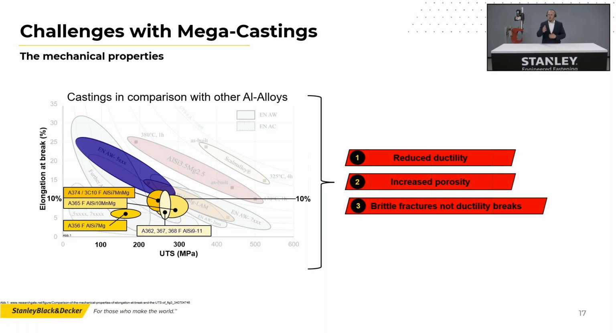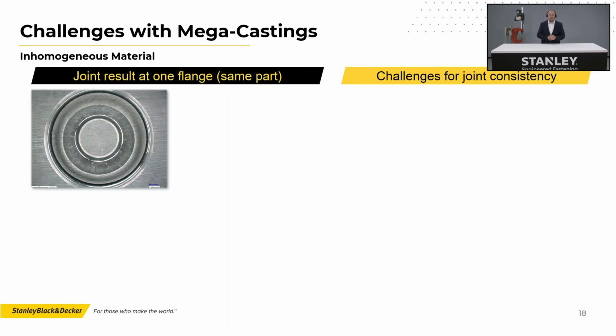But there are even more challenges, and this is why we have to have this webinar. So at the end, there are also challenges in the part design, and the reason for that is that the material itself, the cast itself, is inhomogeneous, meaning if you have one part, it's the same alloy, but depending on where you do the joint or where you do the material testing, is it close to the entry of the aluminum? Is it close to the end of the aluminum? What is the flow direction? Do you test vertical to the flow direction? If you do your tensile tests, do you test in the same direction as the flow direction, etc., etc. So there we see different features and different mechanical properties on the same part.